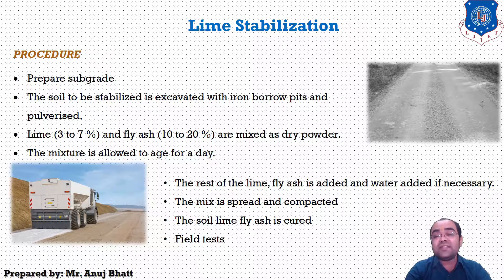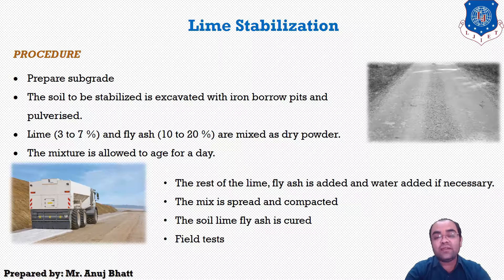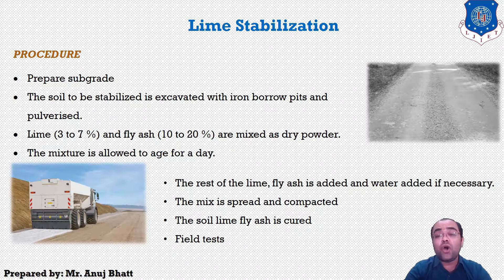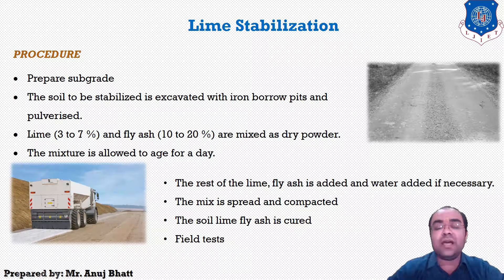The mix is spread and then compacted to the desired grade and camber. The soil-lime-fly ash layer is cured by preventing drying of the surface. Field tests are conducted to check moisture content during compaction and also to check dry density after compaction. Now let's move on to cement stabilization.